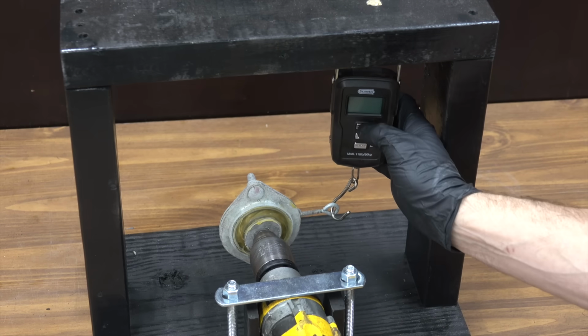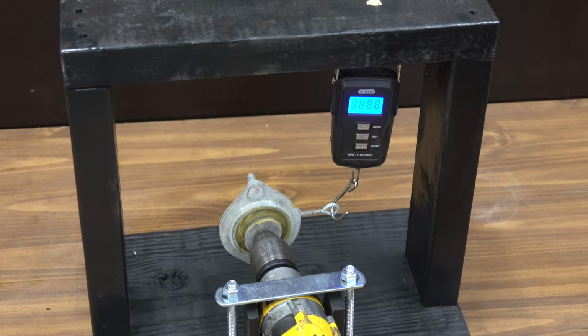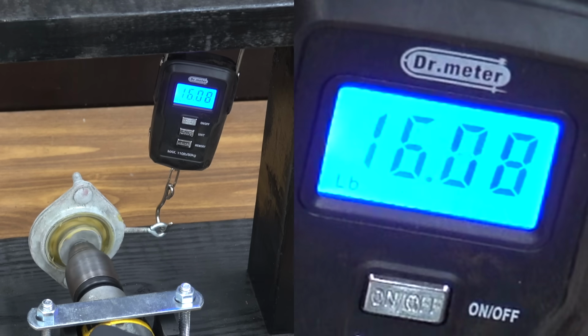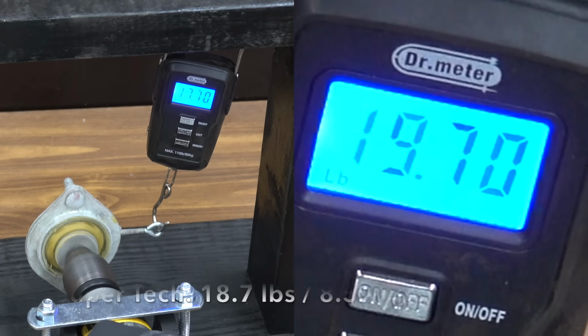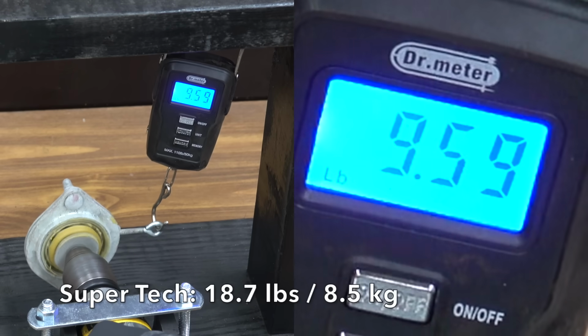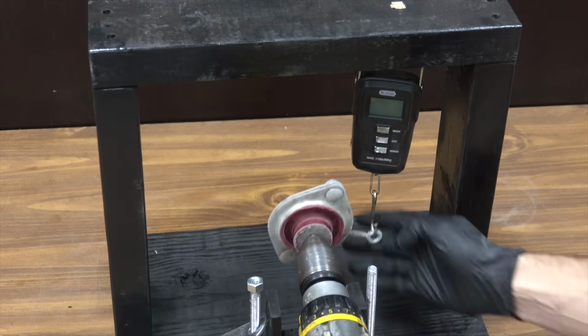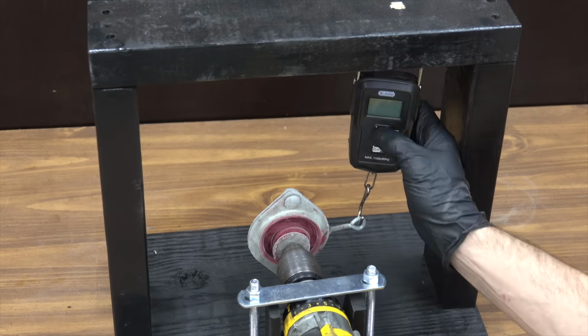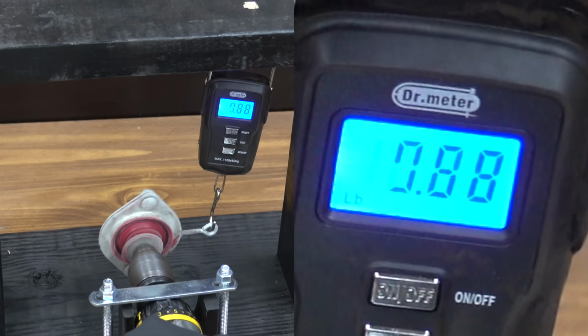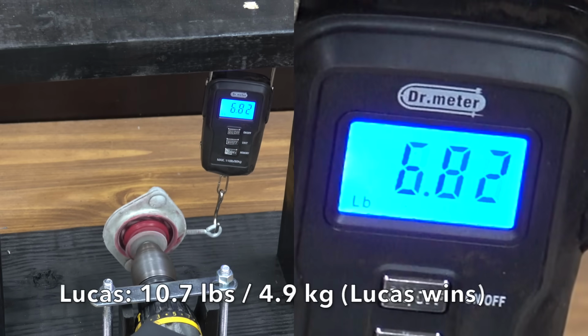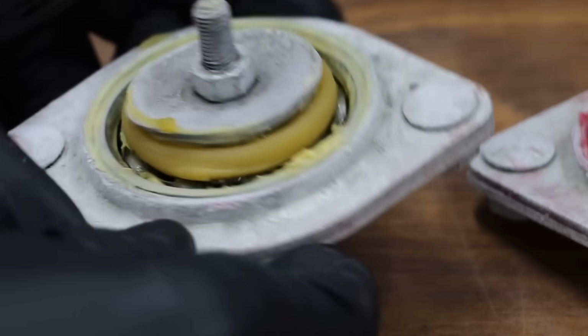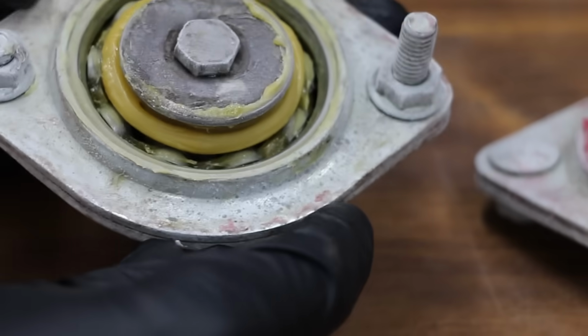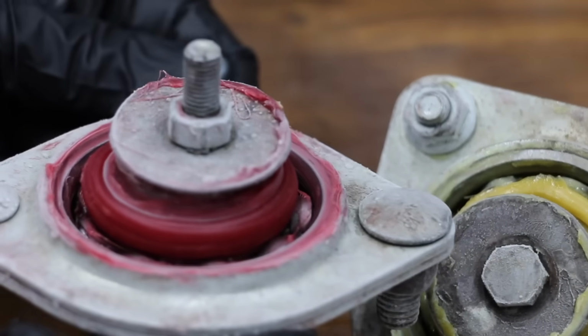The amount of weight recorded by the weight scale will indicate how each brand of grease inhibits the rolling motion of bearings. And the Supertech quickly jumped up to 16 pounds and the maximum recorded weight for the Supertech was a little over 18 pounds. Up next, we'll test Lucas. And Lucas quickly jumped up to 9 pounds and peaked out at 10.7 pounds, but that's still a lot less than the 18 pounds with Supertech. So the Lucas demonstrated better cold temperature performance than the Supertech grease.